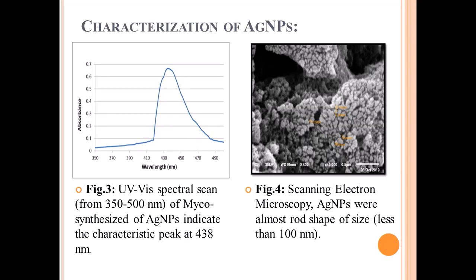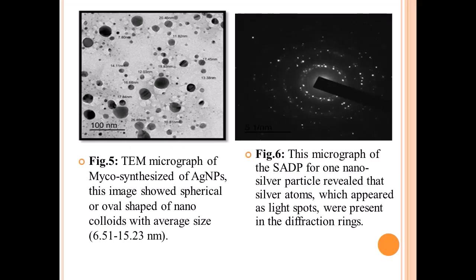Figure 4. Scanning electron microscopy. Silver nanoparticles were almost round shaped, of size less than 100 nanometers. Figure 5. TEM micrograph of myco-synthesized silver nanoparticles. This image shows spherical or oval shaped nanocolloids with average size 6 to 15 nanometers.